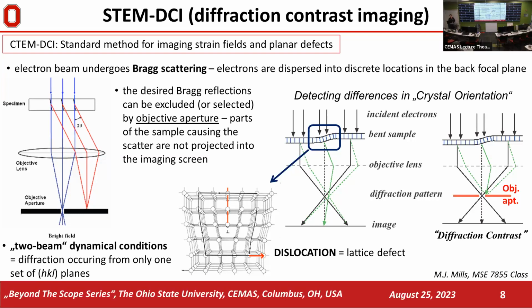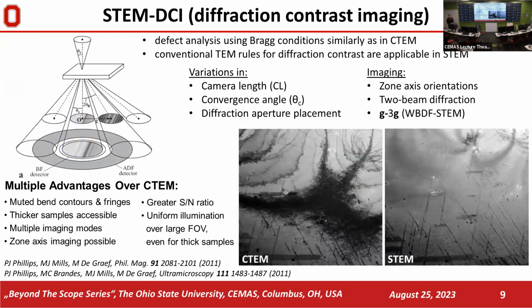So that's quite standard and known, and still a lot of people in the field of metallurgy use conventional TEM diffraction contrast. When we go to STEM, defect analysis using Bragg conditions is similar to CTEM. And all conventional TEM rules for diffraction contrast are fully applicable now in STEM. But there are a lot of advantages over conventional TEM. Some of them are, we have muted bend contours and fringes. We can do much thicker samples than in conventional TEM. We can do multiple imaging modes where you just turn the knob and you transition from atomic resolution, small field of view, large magnification, to a large field of view, low magnification diffraction contrast.